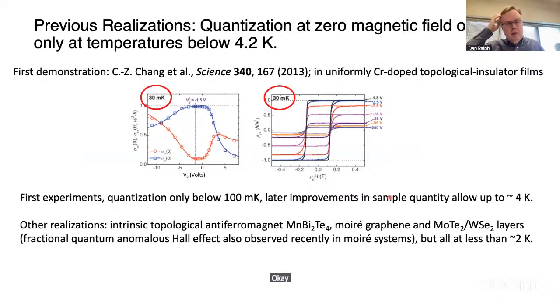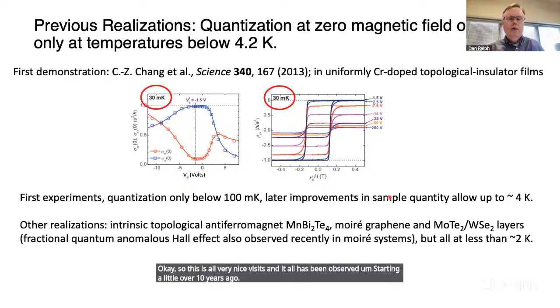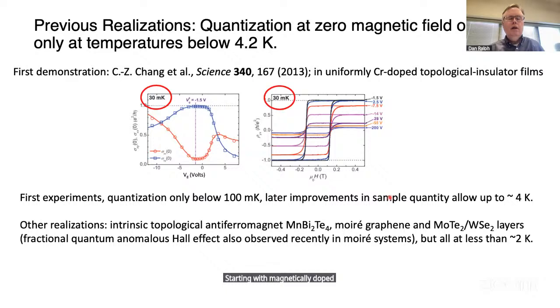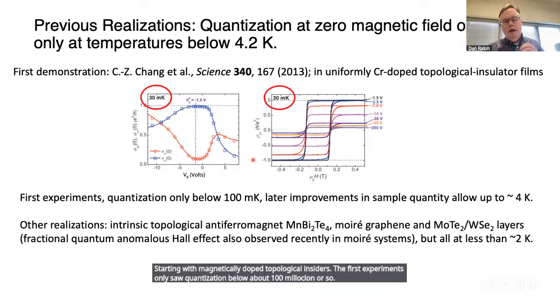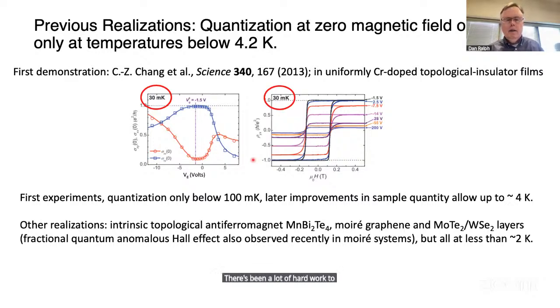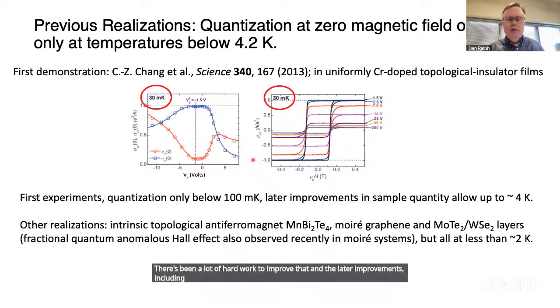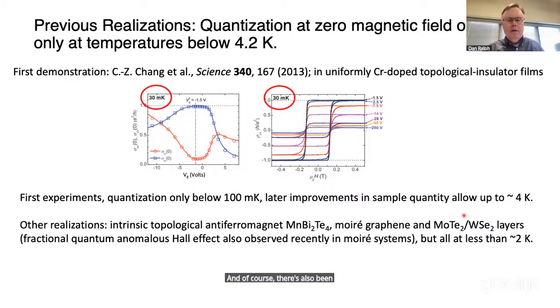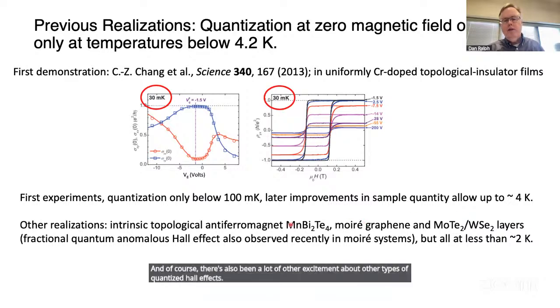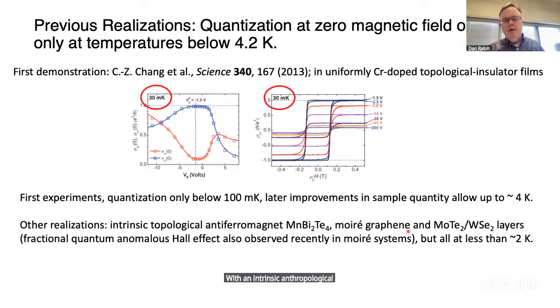Okay, so this is all very nice physics, and it all has been observed starting a little over 10 years ago, starting with magnetically doped topological insulators. The first experiments only saw quantization below about 100 millikelvin or so. There's been a lot of hard work to improve that, and the later improvements, including modulation doping, have allowed these temperature scales to get up to about 4 Kelvin or so. And of course, there's also been a lot of other excitement about other types of quantized Hall effects within intrinsic topological antiferromagnets, moiré systems, and also observations of fractional quantum Hall effect. But all of those have been at temperatures below 2 Kelvin.